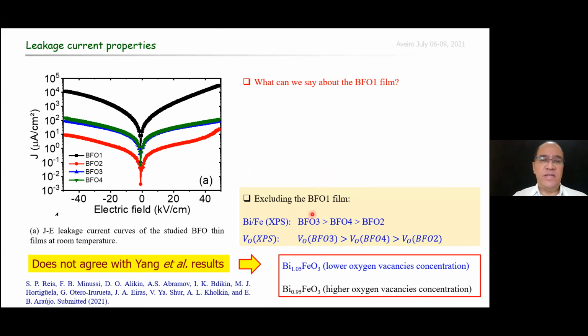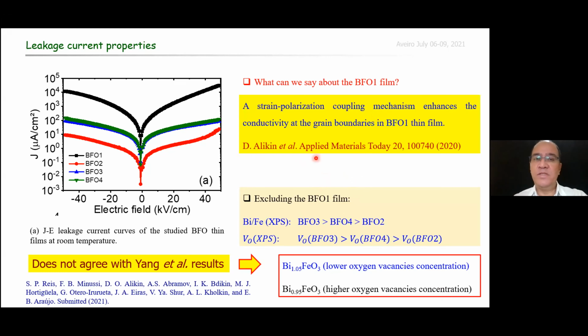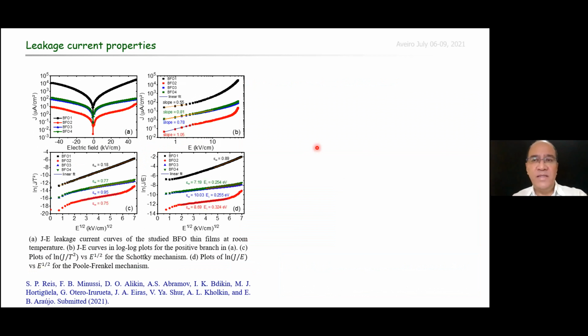We excluded the BFO1 film, but what can we say about it? For this specific sample, we reported in recent work that a strain polarization coupling mechanism enhances the conductivity at the grain boundaries. So additional studies are in progress to better understand the relationship between leakage current in this film and this specific mechanism. Regarding the leakage mechanism, we excluded the SCLC mechanism for all BFO films in this figure B, but ohmic conduction dominates at low electric fields except for BFO1.